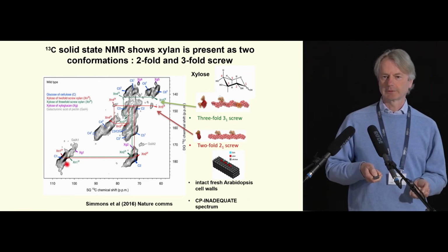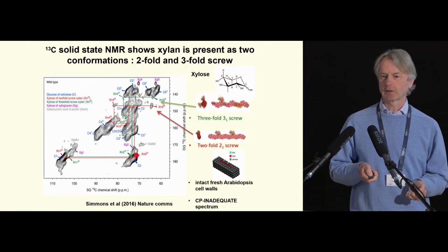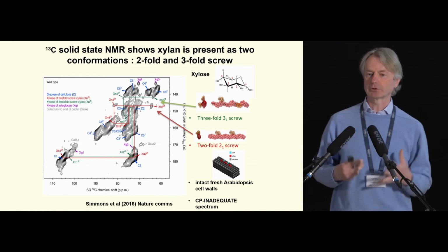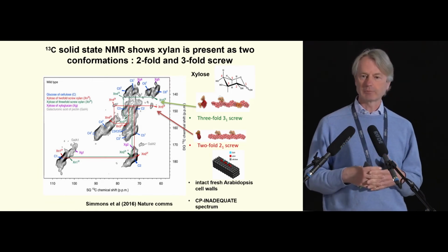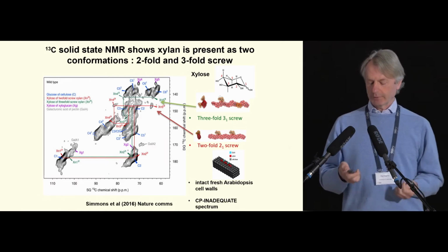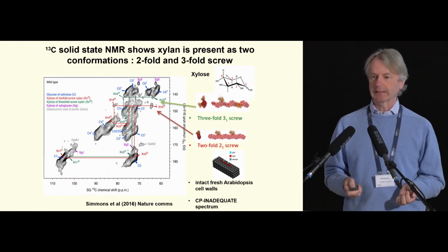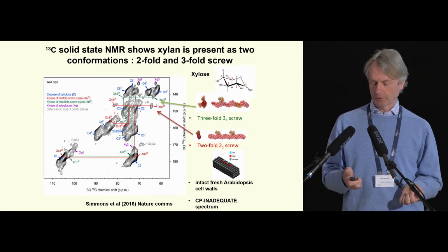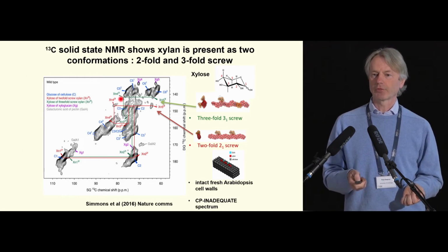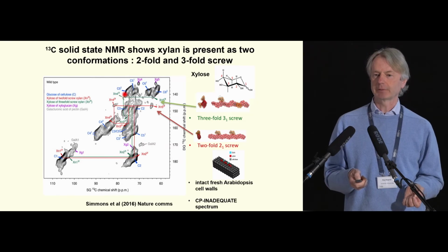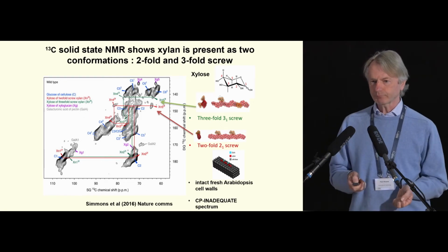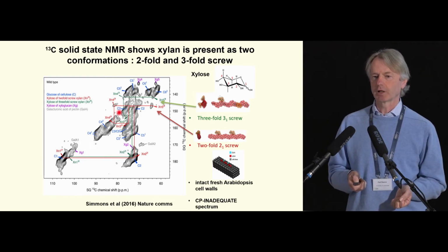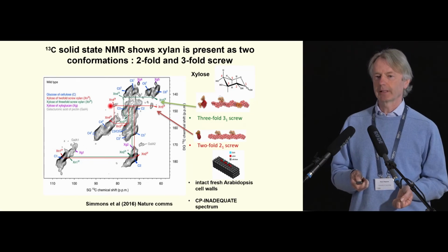It's a bit awkward to use. Here we go: carbon 1 of cellulose and carbon 2 of cellulose here, and we have 2 carbon 4s, which correspond to the surface and interior regions of the cellulose microfibril, for example. Now, what about the xylan? Xylan in solution has well-known carbon shifts, and carbon-3 of xylan is around 78 ppm, and we see this in the cell wall of these plants. But most of the xylan had a different shift of carbon-4, shown here at 82 ppm.